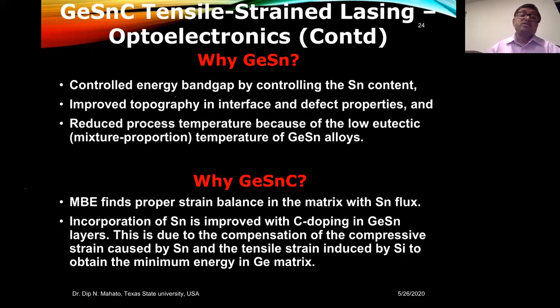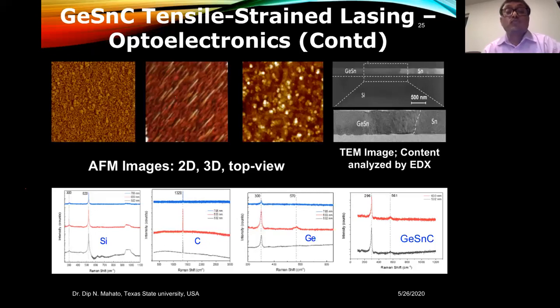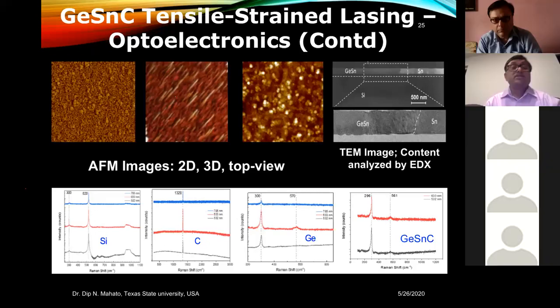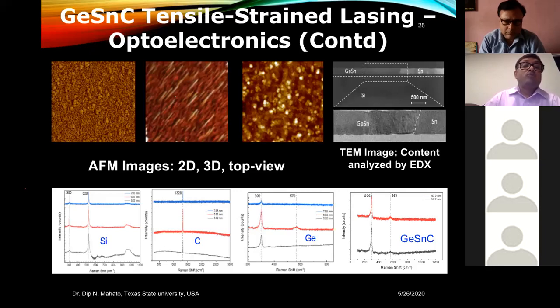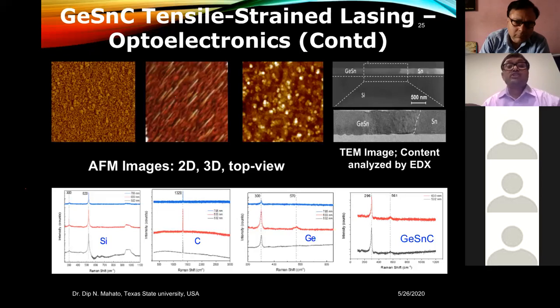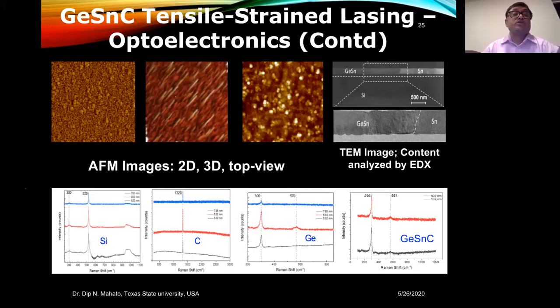So all these things need to be taken into account, and that is what we have done, some work, and this is exactly from our lab. You can see we have deposited and started the growth, and then we have done some characterization also. The 2D image, AFM, atomic force microscopy images. With the naked eye, you will see completely nothing. But when you do the AFM images, you see this: 2D, 3D in the middle, and then the top view on the right.